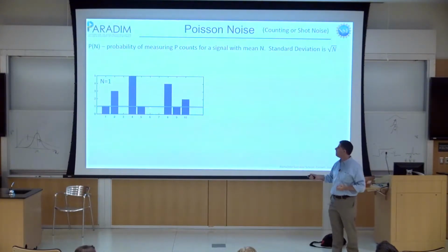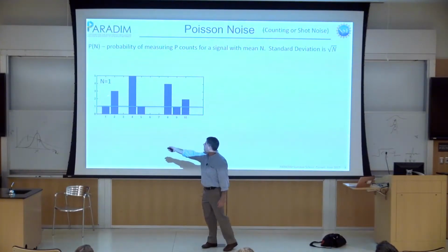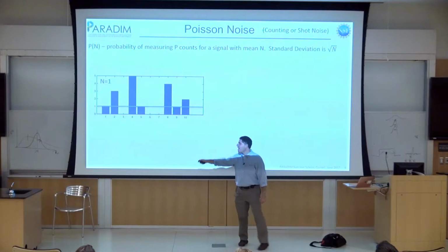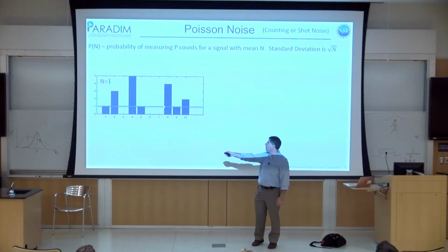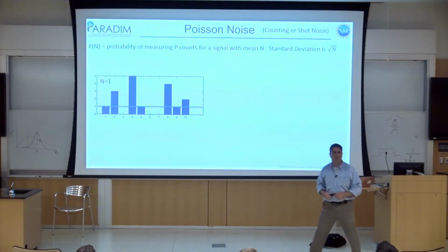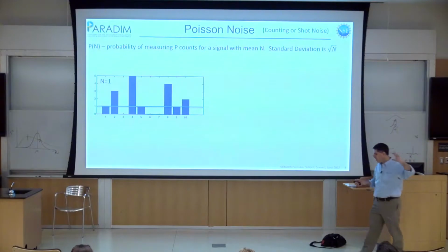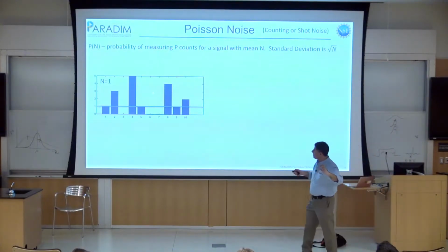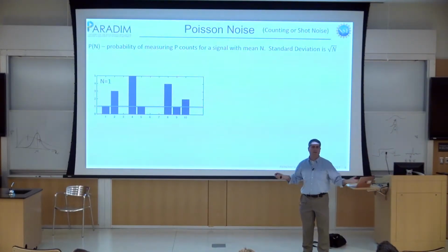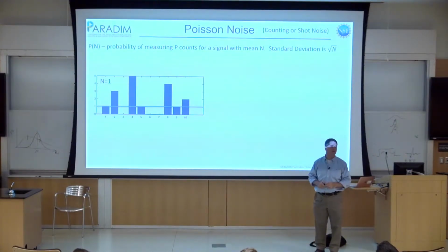Then you'll see all these big blobby features, and you'd go, oh look, in EDX I detected a nice atom here and another atom there, and there's another atom cluster over here, and there's no material in between. That's just all noise, and so you should never let the EDX software smooth your data. You should look at the raw counts, inspect their numbers, and understand whether the statistics are outside that square root of n range. In this case, this is not a bunch of atoms, this is random noise.